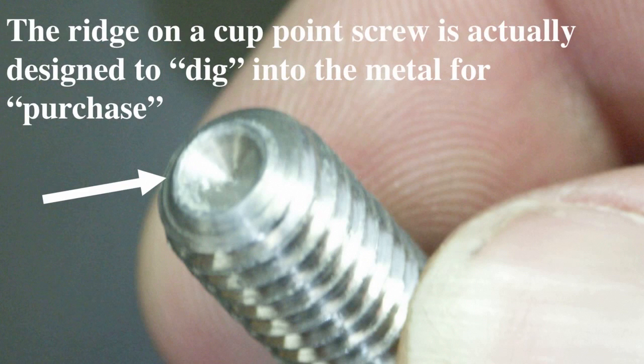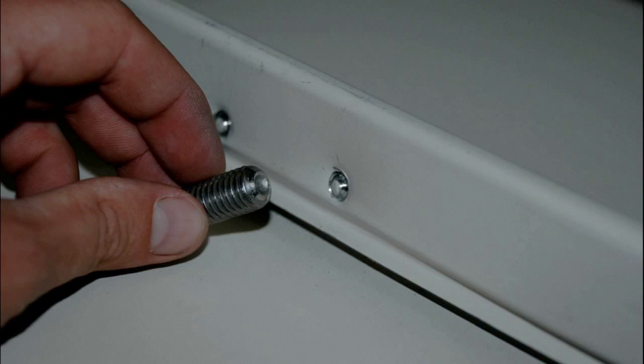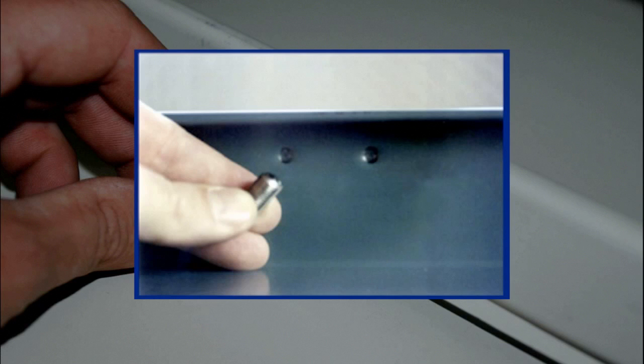Unlike a cup point set screw, which breaches those coatings, violating warranties and creating a corrosion or fracture site, you see the slight depression here made by the round point screw that creates a mechanical interlock without breaking the paint or the protective metallic galvalume coating beneath the paint.